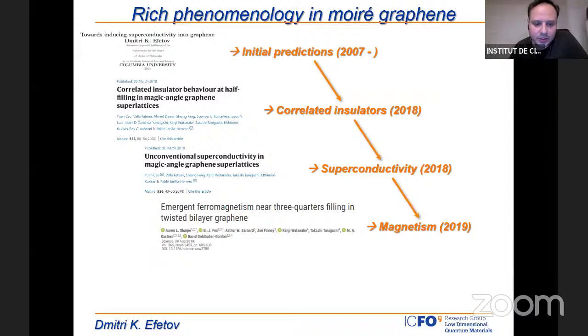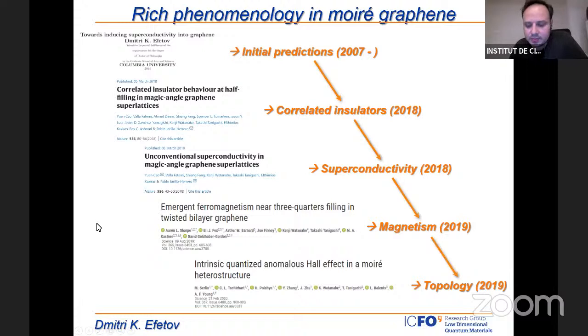And then the story continued, and the system became even richer last year, when several groups reported that these systems can also be magnetic. This was in particular reported by David Goldhaber-Gordon from Stanford. And then this magnetism also introduces some topological states, and anomalous quantum Hall was also discovered very soon after that. So we now have a system which has all these emergent phases. All these phases can live in this very same device. So we can gate-tune between different phases and observe them all at the same time.